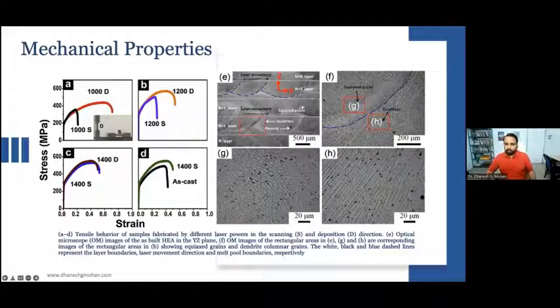And this is a more zoomed version of this H area. You can see the columns, and some black defects over here, some fractures, and these are the fine grains from this equiaxed region. That is, from the G region, more focus is given here. For the H, the dendrites are visible here. They look just like lines. Here they look like small nodules.